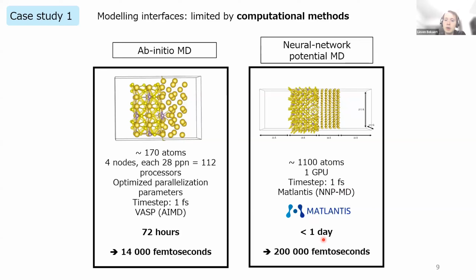In less than a day, we were able to achieve 200,000 femtoseconds. So that's 200 picoseconds. That's a significant increase over the results with ab initio MD. And as a result, we were able to get many more results in a shorter time. And we were able to publish 2 papers this year using Matlantis.